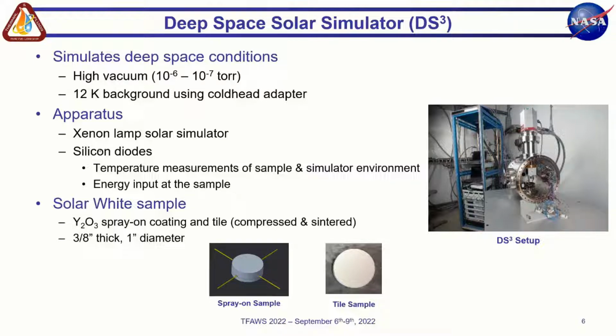As far as the apparatus, there's a xenon lamp solar simulator, which is used, and that's a big part of the model, which I'll discuss later. We have silicon diodes, which we use to measure temperatures of the sample as well as the simulator environment and other components. We also determine the energy input at the sample. For the solar white sample, we analyzed two different samples, a spray-on coating and a tile. For the spray-on coating, the yttria powder was sprayed onto a small aluminum cylinder, as shown here. The rigid tile samples, like the one shown here, were created by compressing and sintering yttrium oxide. Both samples were 1 inch in diameter. This sprayed sample was 3/8 inches thick. I believe the tile was 1/2 inch thick.